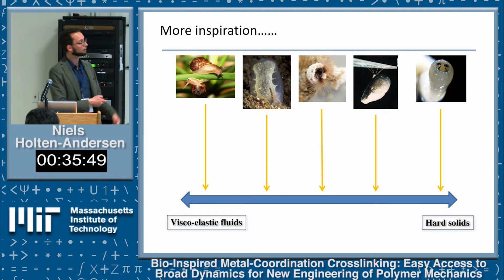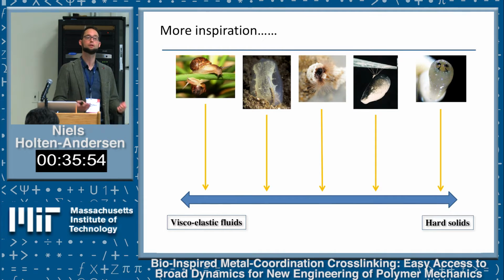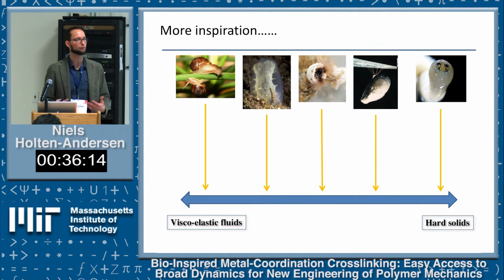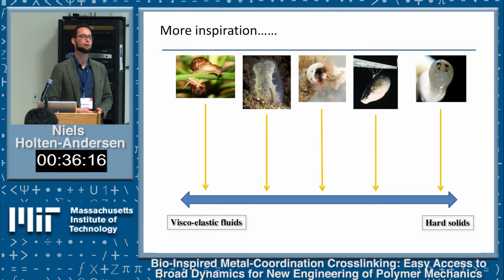So we've begun playing a little with this. If we dehydrate some of the gels, just get rid of the solvent, what we're left with is, not surprisingly, stiffer because we removed the solvent, but it's much stiffer than we'd expect, and it's still energy dissipating. We've begun exploring what happens to these processing structures once you remove the solvent. This is something biology plays with a lot in materials manufacturing - it makes things in a wet, hydrated state, and often there's a dehydration gradient that makes the material stiffer while still retaining some of the material properties.